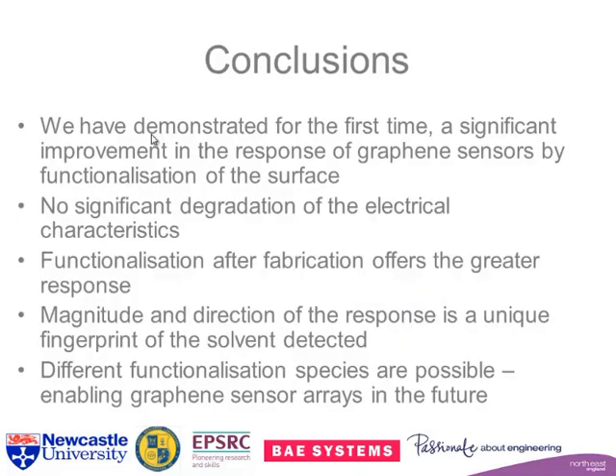So to conclude, well, for the first time we've shown a significant improvement in response of a graphene sensor. We haven't degraded the electrical characteristics at all. Functionalization after fabrication offers the greatest response, but also at the same time offers by far the greatest challenge in processing. So those of us who work at the sensor end think it's great, and the lads in the clean room are less happy. The magnitude and direction of response is a unique fingerprint. We've identified that the dipole moment allows you to identify uniquely which materials you've got.